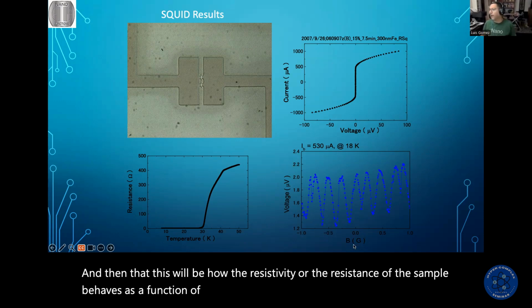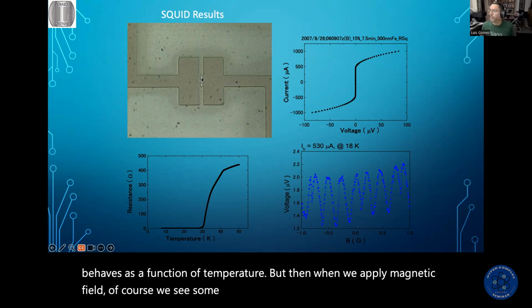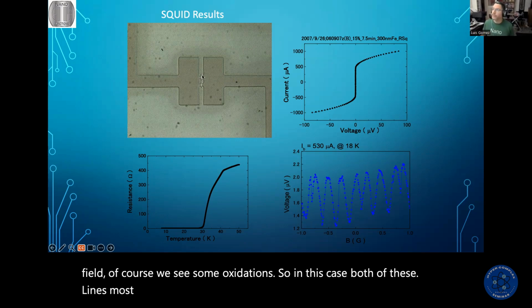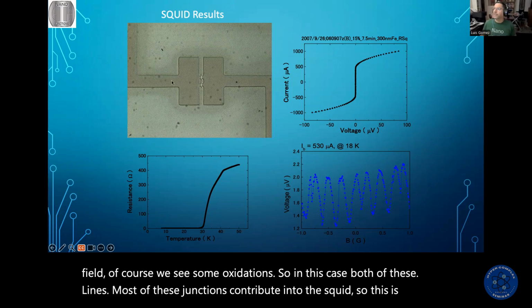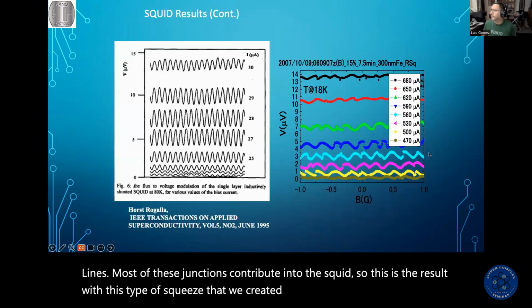But then when we apply magnetic field, we see some oscillations. In this case, both of these lines, or both of these junctions, contribute to the SQUID. So this is the result with this type of SQUID that we created using these junctions.